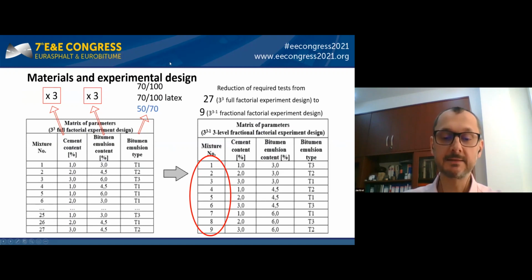For tests, we designed a full factorial experiment based on 3 parameters: cement content 1 to 3%, bituminous emulsion content 3, 4.5, and 6%, and type of emulsions. The first two emulsions, the black ones, used for research were typical, but the third was experimental, based on harder 50/70 bitumen, that's the blue one. This full experiment was next reduced to 9 compositions based on the fractional factorial experimental design method. This allows us to reduce the number of tested cases and overall number of specimens.